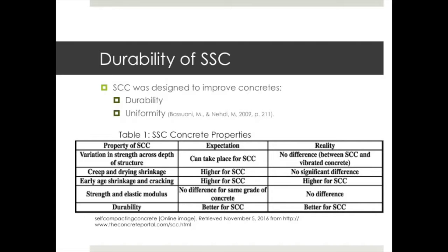The creep and drying shrinkage was expected to be much higher for self-consolidating concrete than it was for conventional concrete. However, the reality is there is no significant difference between the creep and the drying shrinkage in the self-consolidating concrete and conventional concrete. The strength and elastic modulus of self-consolidating concrete is equal in comparison to conventional concrete. Self-consolidating concrete was predicted to be much more durable than conventional concrete, which has been proven through a variety of different experiments.